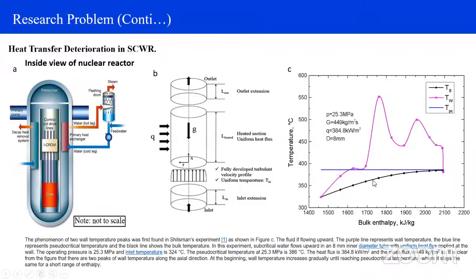The heat flux is 384.8 kW per meter square, and the mass flux is 449 kg per meter square second. It is clear from the figure that there are two peaks, like one peak is this one and the other peak is this one. Two peaks of wall temperature along the axial direction. At the beginning, wall temperature increased gradually until reaching the pseudo-critical temperature, where it stays the same for a short range of enthalpy.